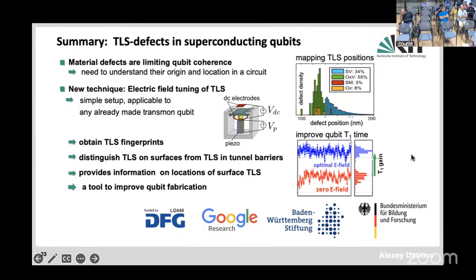And I noticed that most of the TLS defects are on the superconductor surfaces, about 60%. Right. So wouldn't it be better if you have a superconductor which does not form oxide? Well, that's what people now try to do with tantalum. So tantalum does not form oxide that aggressively. Of course, there is some oxide formed, but it's not that significant as with aluminum or with niobium. So people are trying to search for better superconductors. They're trying also to passivate the surface using different techniques.